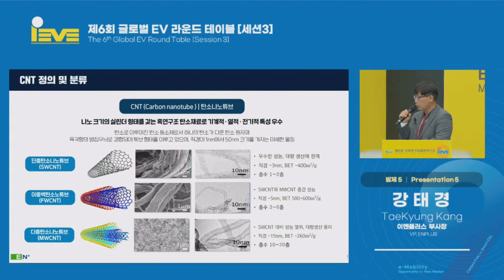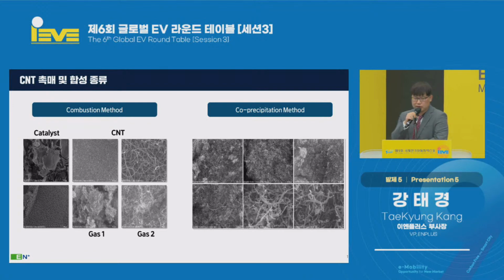Single-wall CNT, few-wall CNT, multi-wall CNT. As for multi-wall CNT, it is most widely used. Single-wall CNT seems to have excellent conductivity, but it's very expensive. So we are looking for something hybrid between single-wall and multi-wall. And CNT itself is synthesized using a catalyst. We have been studying this for 15 years, and there's the combustion method and the co-precipitation method.